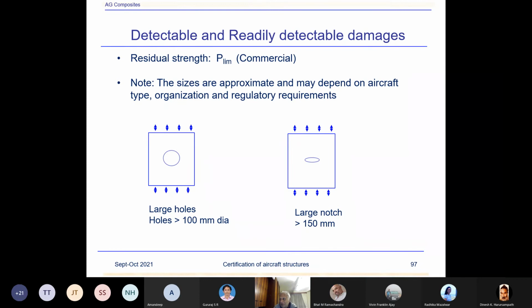All these repairs, when we specify, we qualify the repairs by initial testing. Suppose you have a flap, with different thicknesses in different regions and different layups, and the damage could be anywhere. So we have defined, okay, in this damage zone, and this is my damage limit, like you can have a 2-inch hole or 3-inch hole, and airlines have to repair that 3-inch hole. We provide the repair scenario, how they will repair, what kind of layup and what kind of material they would use. And that repair which we have designed, which airlines will do, will already meet the ultimate load requirement.